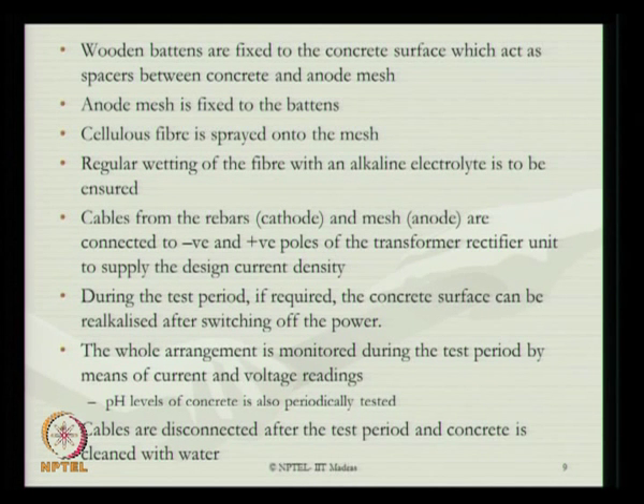Cables from the rebar, which we call the cathode and which are generally black in color, and the mesh, which we call the anode and which are generally red in color, are connected respectively to the negative and positive poles of the transformer rectifier unit to supply the design current intensity. During the test period, if required, the concrete surface can be realkalized after switching off the power, if you see the electrolyte is getting dried off because of weather conditions. The whole arrangement is then monitored during the test period by means of current and voltage readings. The pH levels of concrete are also periodically inspected and tested.